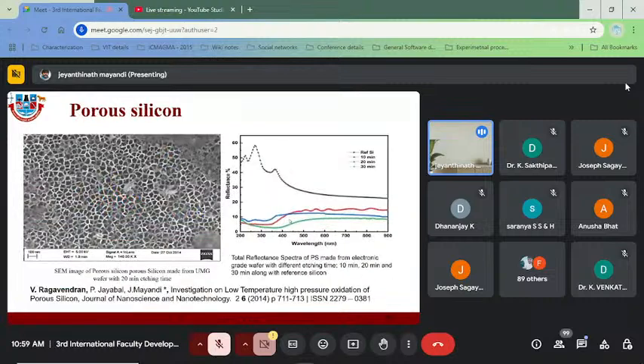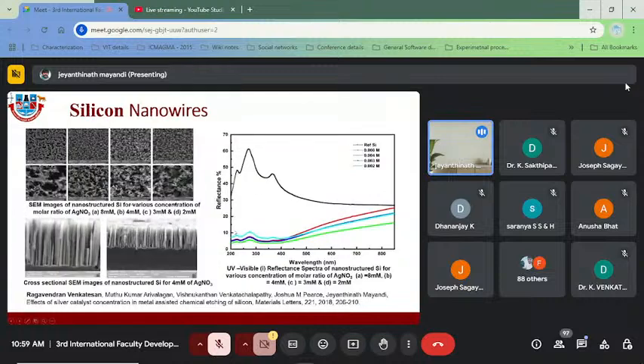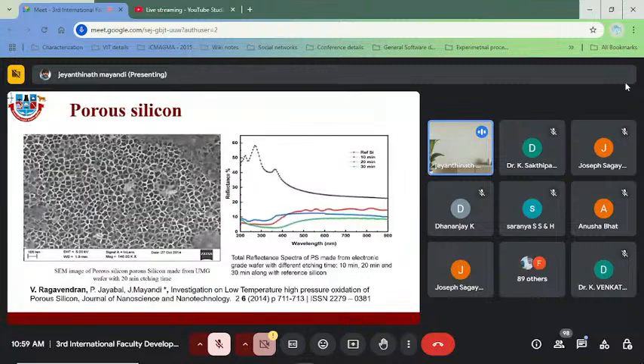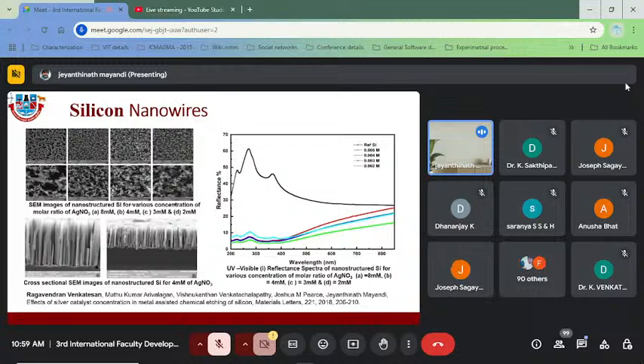And then we tried to do it in our laboratory, and we could make interesting network-like structures. You could see our starting reflectance is around 30 to 60 percent after this treatment of the wafer, and after 30 minutes of etching, we could reduce it to less than 10 percent reflectance. Similarly, we were also able to make nanostructured wires or pillars. The earlier one was done by electrochemical etching, whereas this was done by metal assisted chemical etching.